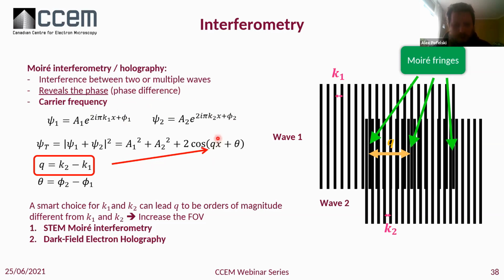But you have this other component, which is the carrier frequency. That is actually the difference of the wave vectors. This is something that we don't put much attention on, but this is actually the argument that is used to increase the field of view. Because if you make a smart choice of K1 and K2, you can get a Q element that is orders of magnitude different from K, especially if the Ks are close to each other. And that's the idea of increasing the field of view.